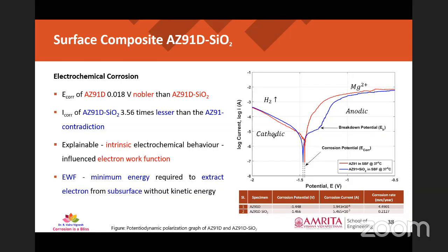So we thought of analyzing the surface using the atomic force microscopy, AFM technique. So we have done some surface potential analysis using this AFM probe. So this is explained on the basis of the intrinsic electrochemical behavior of the material, which is influenced by the electron work function. Okay, and this electron work function is the minimum energy required to extract an electron from the subsurface of the material without the use of kinetic energy.